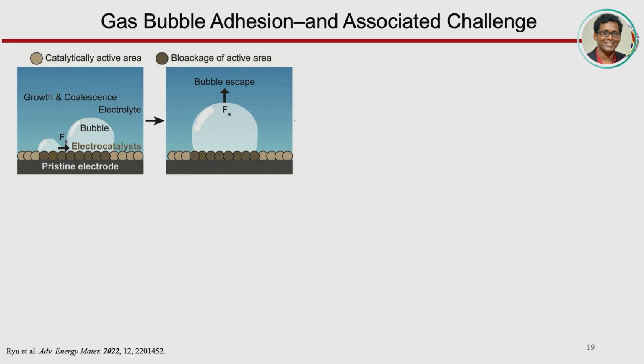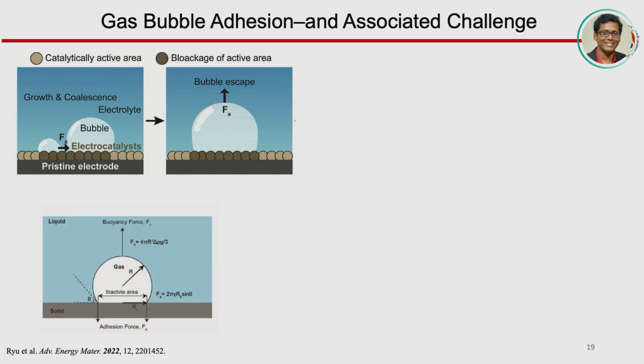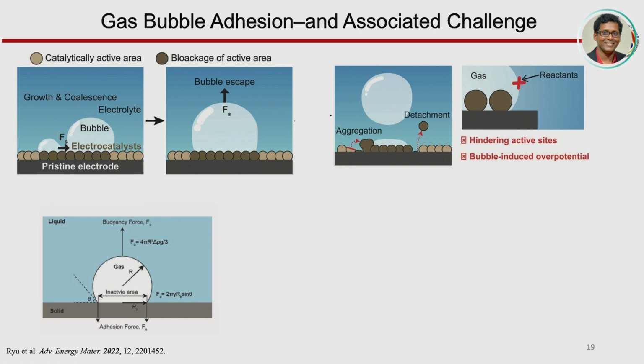It's because the buoyancy force drags it out from the surface, right. So this is the same mechanism here. The bubbles are forming and becoming bigger and bigger. That means the buoyancy force is becoming predominant and compensating this adhesion force, and that's the reason it's detached. But during that process, millions of bubbles are coming out, and the catalyst will feel some sort of shear stress. And if you are physically depositing some state-of-the-art catalyst, it is naturally going to detach, right? So the performance of the electrode will be a problem.